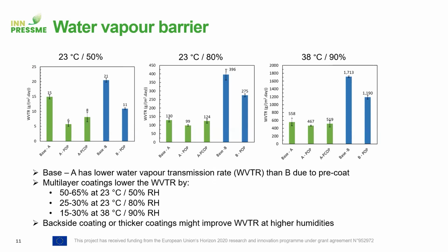Then to the water vapor barrier. We see from these images three different images in different relative humidities. We tested the water vapor, and in green are the coatings on base paper A, and in blue the coatings on base paper B. Compared to the reference, only the paper, when we apply the coatings we get a decrease in the water vapor transmission in all of the relative humidities, and the clearest decrease, 50 to 65%, is at 50% relative humidity. With base paper A we get slightly better values because there is a pre-coating that also enhances the water vapor barrier.